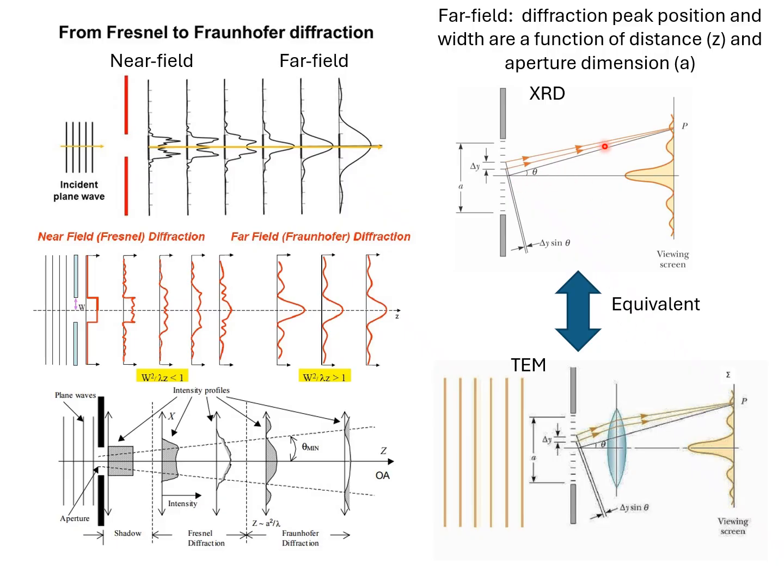If we consider the direct superposition, which would be the case in X-ray diffraction, this would be a very large angular range and we'd be sampling the intensities. But when it comes to electron microscopy, we're making use of lenses, and by using a lens, we can focus rays that are coming off at the same angle, and it gives you the same answer in effect, and focus them to a point on the back focal plane at the imaging plane where we see a diffraction pattern.